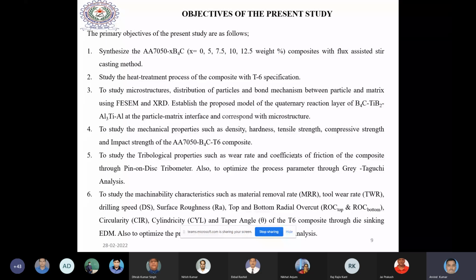Then through flux assisted stir casting, we have gone for heat treatment. Then several mechanical testing we have gone for. And basically for the bond formation mechanism, we have tested through several XRD. Then we have gone for FESEM, and we have established a quaternary layer of B4C, TiB2, Al3Ti, aluminum titanate and aluminum particle matrix interface, and the microstructure. I have published one paper on this, and that was highly recognized.